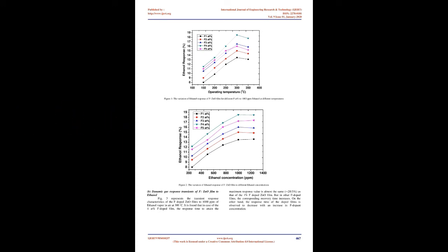A 0.5 M solution of zinc acetate dihydrate, Zn(CH3COO)2·2H2O, diluted in methanol and deionized water, 3:1, was used for all the films, and ammonium fluoride, NH4F, was added to the starting solution for fluorine doping. Zinc acetate dihydrate and ammonium fluoride solutions were mixed together in different volume proportions ranging from 1% to 5% in steps of 1%. Air was used as the carrier gas, at a pressure of 0.2 bar. The ultrasonic nozzle to substrate distance was 28 cm, and during deposition the solution flow rate was held constant at 3 ml/min.